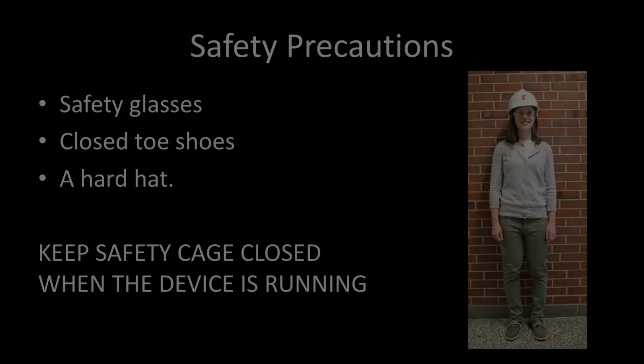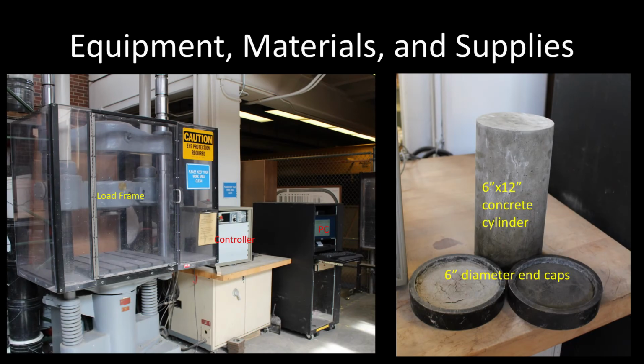The following equipment, materials, and supplies are required for compressive strength testing: a 6-inch by 12-inch hardened Portland cement concrete cylinder, 6-inch diameter end caps, a testing machine capable of applying a controlled rate of loading, a system capable of measuring and recording the ultimate load applied to the specimen.